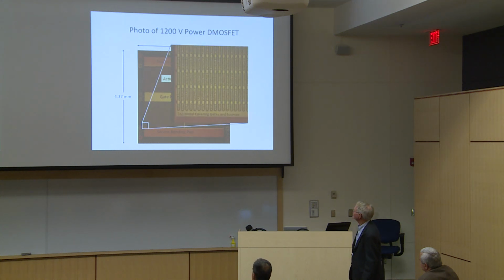But if you take a small area and you blow it up, you can see a little bit better what's going on. Now, this granular-looking thing here, that's supposed to look like that. This is the nickel. When you anneal it and make a good ohmic contact, you get these grains, and it's perfectly normal. But these little gaps here, that's where we dropped in the P+ contact. So we don't have nickel, we've got aluminum here. And so the source contacts are fed vertically. The polysilicon gates run down in between. So this edge here is a transistor, and the edge here is a transistor, and this one is a transistor, and they're all in parallel. And the whole thing is covered with gold top metal.